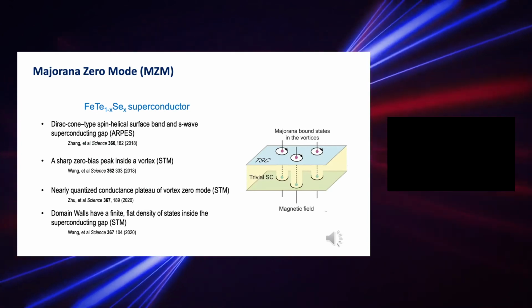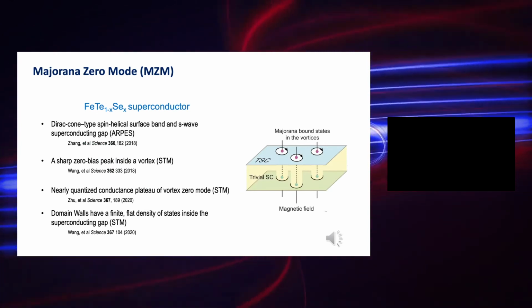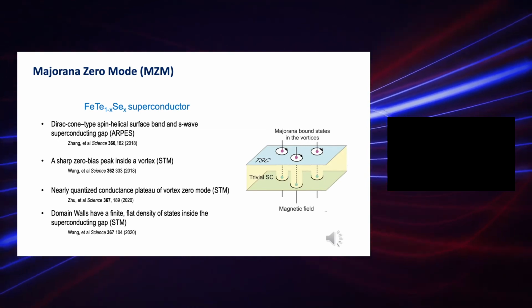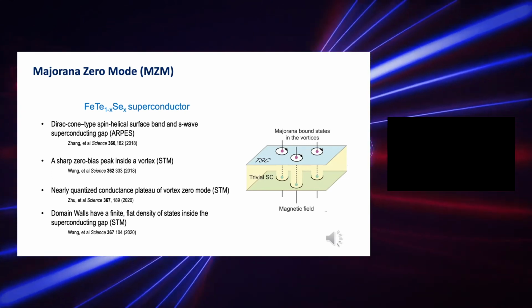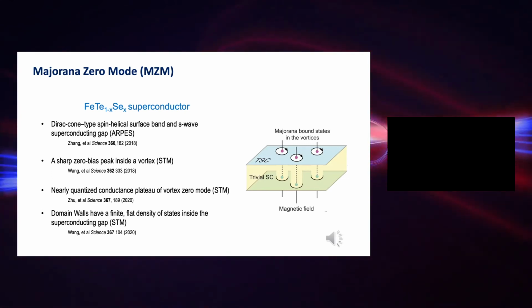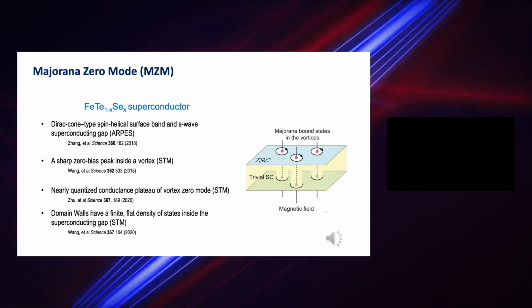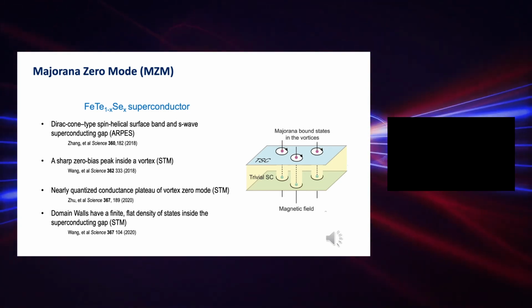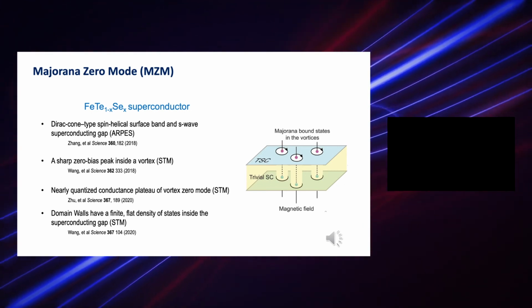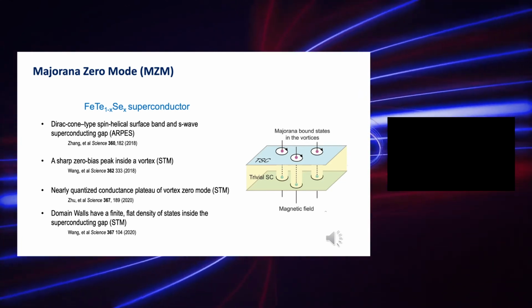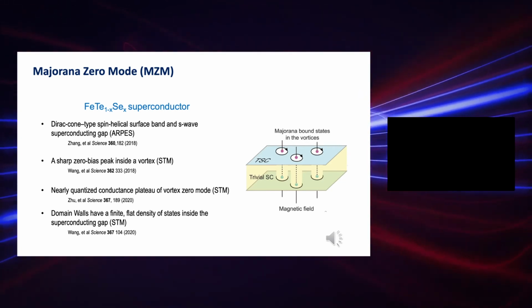The evidence of Majorana zero mode has also been reported in multiple publications involving iron chalcogenide superconductors using the same single crystals grown in our group. Now, the Majorana zero mode is proposed to be present at the end of these magnetic vortices. A manifestation is a sharp zero bias conduction peak within the vortices. But why do we have to use iron chalcogenide? That's because they have all three ingredients necessary to produce Majorana zero mode. Of course, the debate is still going on in the interpretation of the data, which I will not get into.